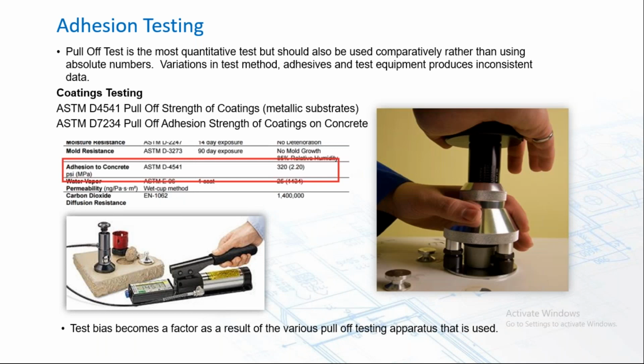Adhesion testing. It'd be great to know that the products we're specifying actually adhere to the concrete substrate to which they're applied, and it's a great test because it provides you a quantitative result. It gives you a hard number that, hey, it requires this many PSI to remove this coating from this facade. Unfortunately, there are 5 different test apparatus, and a testing bias now becomes a factor as a result of the various apparatus that are used. But it's great again for a comparative test where you have competing manufacturers on the wall, or you want to test the adhesion of the existing coating versus the effects of applying the new coating. But as an absolute number, there's not a lot of frame of reference there.